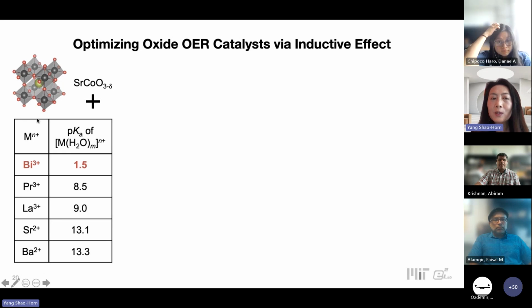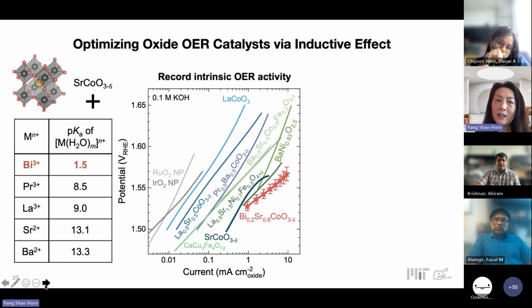One example is, let's look at the cobalt perovskite. So we can substitute, let's say, 3+ ions into the A site. And you can choose different types of 3+ A-site ions. So bismuth 3+ is the most acidic. And this would essentially pull the electron density from oxygen away from the cobalt ion. This in turn would give a different covalency between cobalt and oxygen. And utilizing bismuth strontium cobaltite, we note it has really the highest OER activity for the cobalt perovskites, also in terms of oxides normalized per surface area.